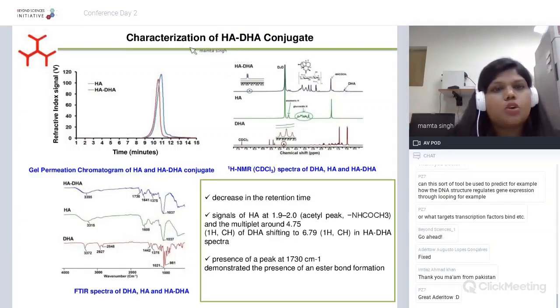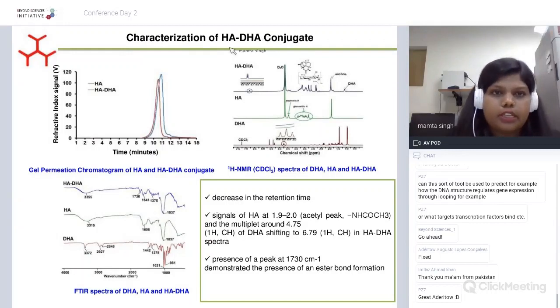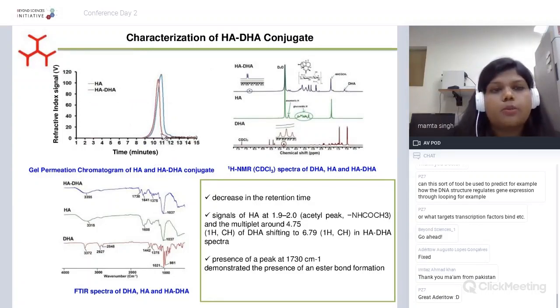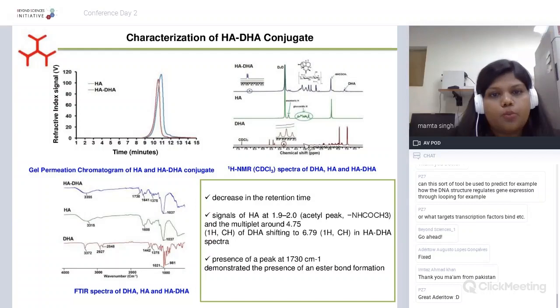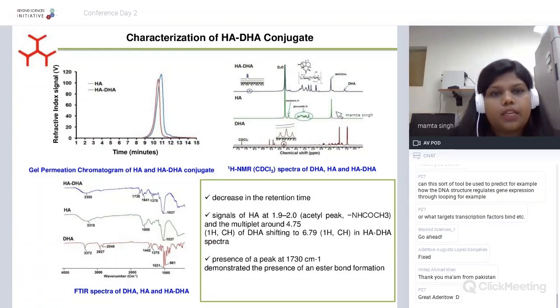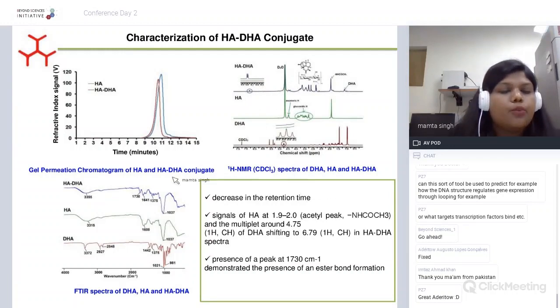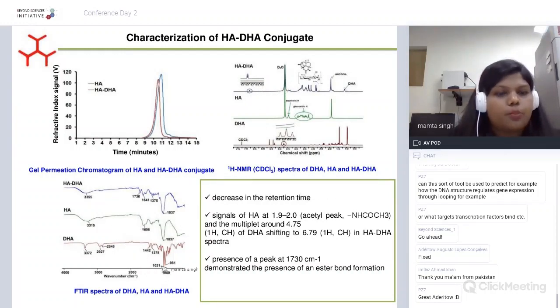The synthesis of the conjugate comprising hyaluronic acid and dihydroartemisinin was confirmed using gel permeation chromatography (GPC) — there were differences in the retention volumes due to incorporation of the DHA moiety. We then did NMR spectroscopy for bond identification: the characteristic acetyl signature peak representing HA was also present in the conjugate, and there was shifting of multiplets from 4 to 6 in the final product, confirming bond formation.